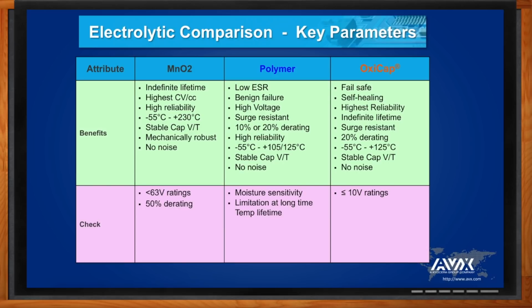The polymer, you have to be concerned about environmental. In the last couple of years, we've got an AEC Q200 capable part, but the commercial parts don't have the same moisture resistance that the standard tantalums do. And for the Oxicap, there's no downside. It's great, except that it's only available up to 10 volt ratings. The dielectric is thicker per volt, and you can't grow such thick dielectrics for higher voltage. So for digital applications, it's a golden technology, but not for high voltage.